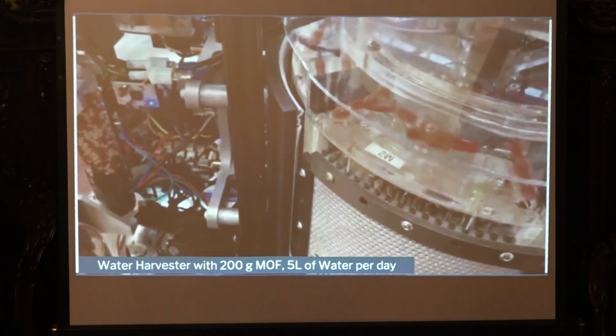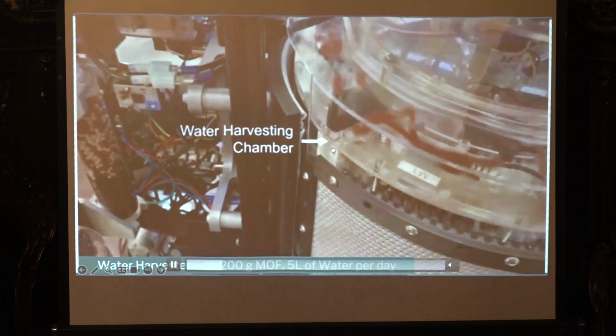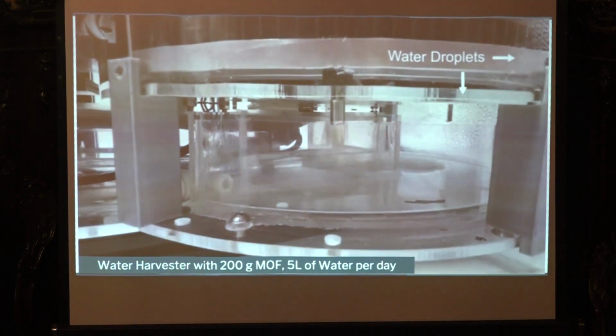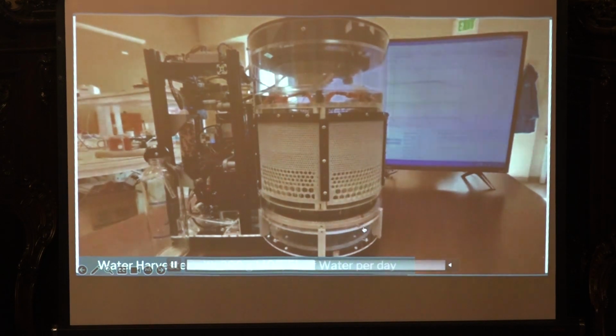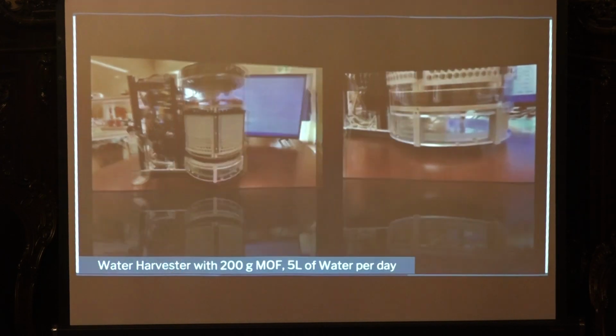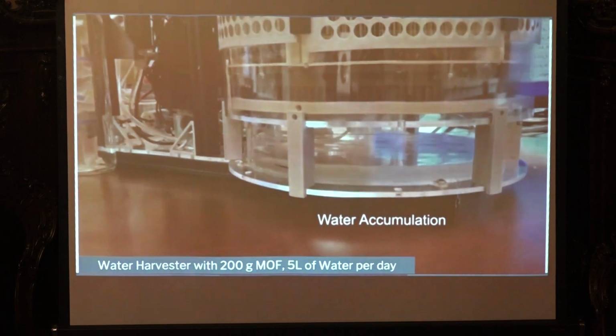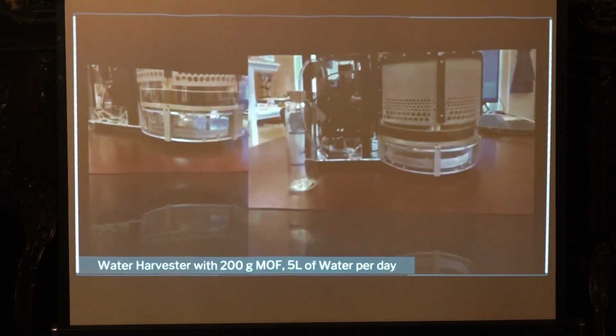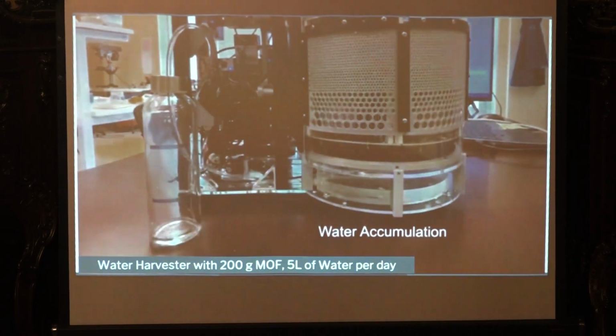In this machine, you can see a door open where air goes in. The air goes into the MOF, and the MOF is heated. You can see the condensation there of the water coming out of the MOF. Then you'll see a puddle. The reason it's rotating is that you have more than one module of MOF. Here's a puddle of water resulting from this MOF.